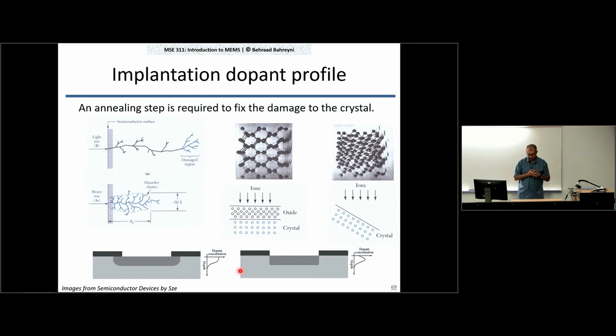and you stop it relatively quickly. In terms of the final profile, with diffusion, if you have an opening, the dopants will go sideways as well as downwards. So you get a little bit of doping beyond the edges of your opening. Ion implantation lets you just go down straight. Yes, you will have a little bit of diffusion during the annealing step, but that can be minimal. And therefore, you have more control over the profile of your doped regions. And therefore, in microelectronics, almost exclusively nowadays, we use implantation whenever you want to have control over doping and doped regions.